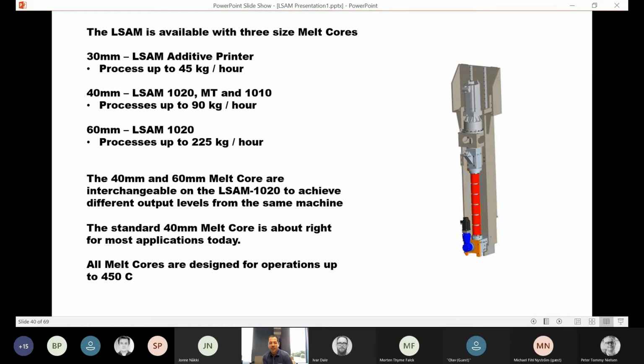And then on our standard flagship model, the LSAM 1020, there's an option to increase that melt core up to 60 millimeter, which will allow you to process up to 225 kilograms of material an hour. The 40 and 60 millimeter melt cores are interchangeable, and that allows you to achieve different output levels from the same machine. Those melt cores can be swapped out in about 6 to 8 hours time. And all our melt cores are designed for operation up to 450 degrees Celsius.